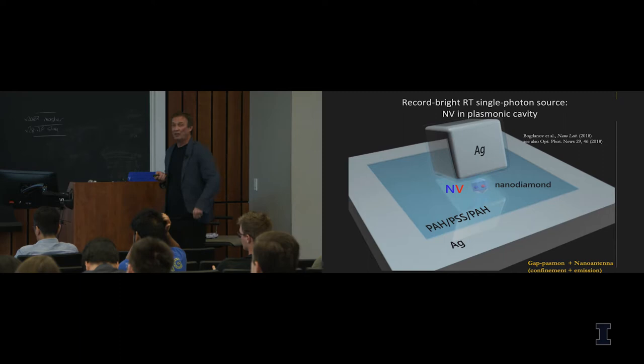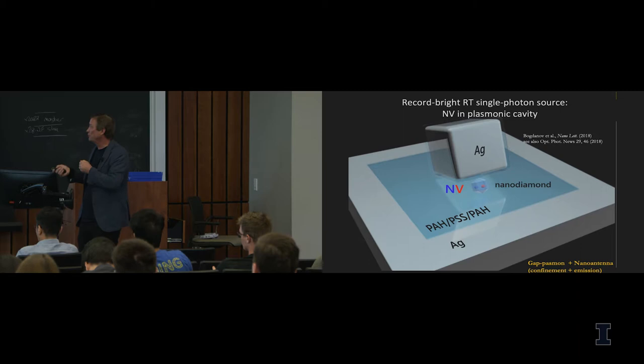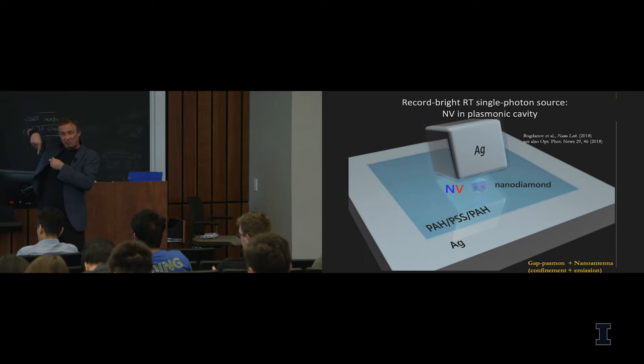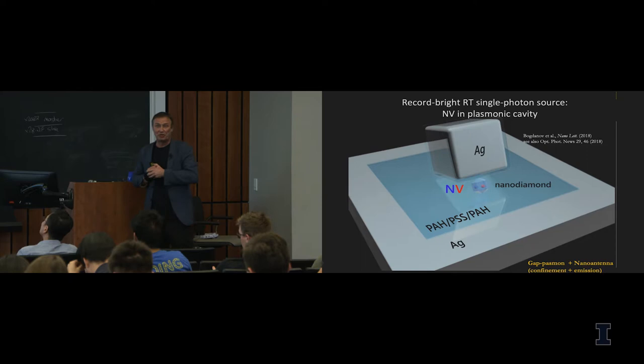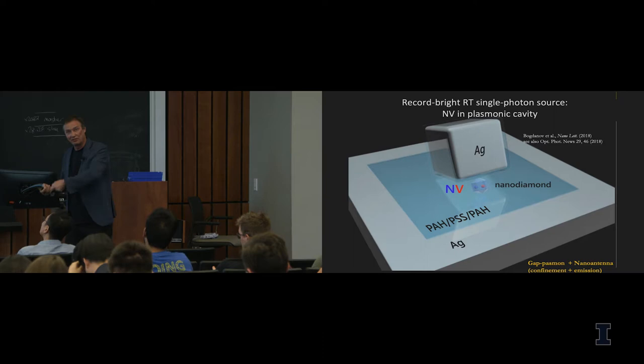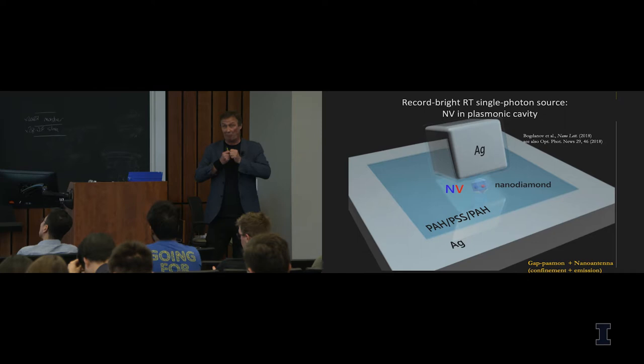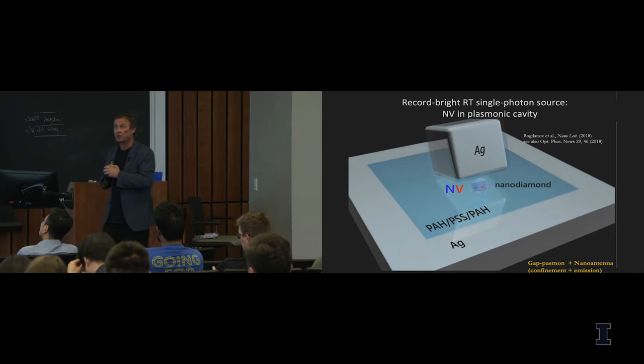But the other trick is not only to have a strong increase in light-matter coupling, but you also would like to outcouple these single photons before decoherence happens. So it means that this antenna should be very efficient. It actually should match the impedance between these plasmonic modes, gap plasmons, and free propagating modes. For that, the antenna should not be too small. It's roughly 100 nanometers. Then you would create these single photons at terahertz rate in the antenna, and outcouple these photons into free space or a waveguide at the same rate before decoherence happens, and ideally before any plasmon decay happens. In principle, according to the calculations, it certainly should be possible. So it's like loss-free plasmonics at rates that beat decoherence.